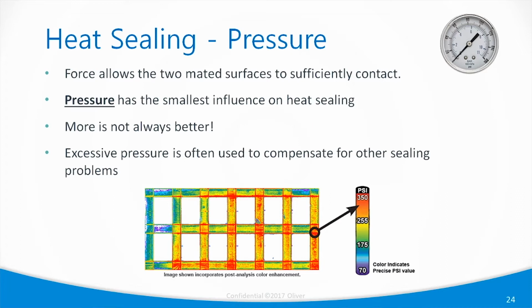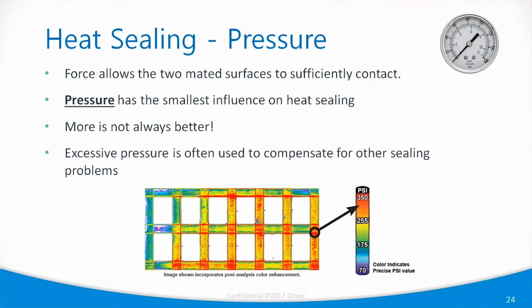Pressure is really just there to get the two materials to mate together and allow the heat and the dwell time to work together to make a good seal. So just be careful with pressure. Too much pressure is a problem. If you think about impacting the materials with too much pressure, you can get that adhesive to go up into the fibers of the Tyvek. You can get it to squeegee out from the seal, and that means you have less adhesive at the interface, which makes potentially a less robust seal altogether.